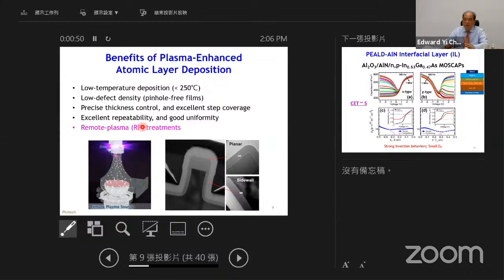Okay, so the way of doing it on our side is using plasma enhanced atomic layer deposition, ALD. So this technology has low temperature deposition and very low defect densities and precise thickness control and excellent step coverage. And also it's very reproducible. And we were able to use this tool to do remote plasma treatment on the surface. So you can get very good DIT with good film quality.